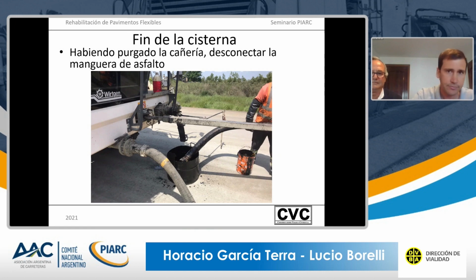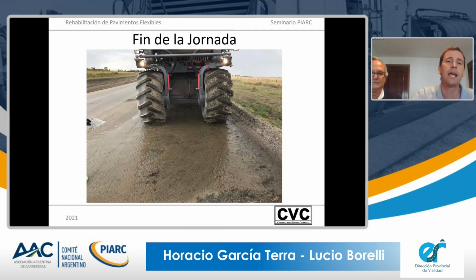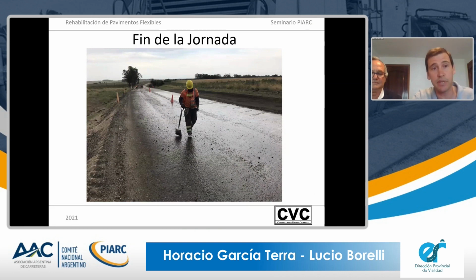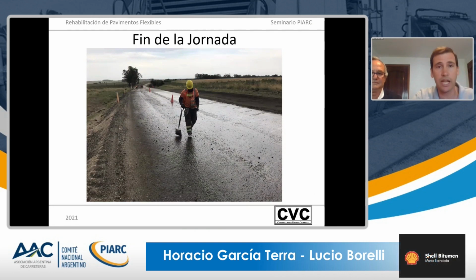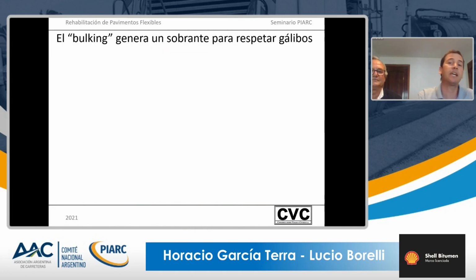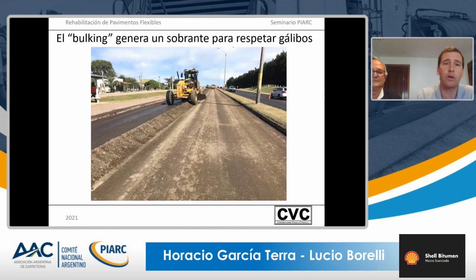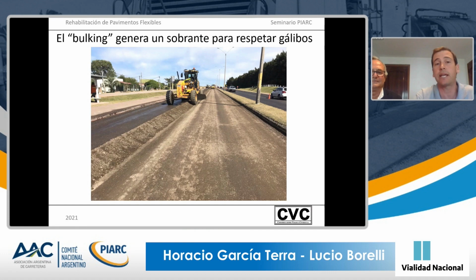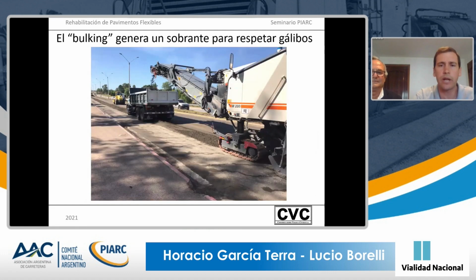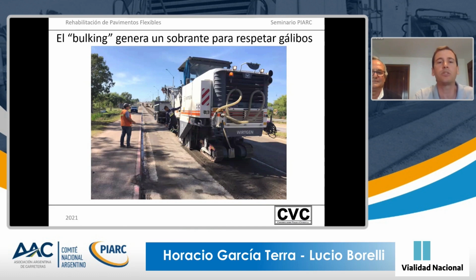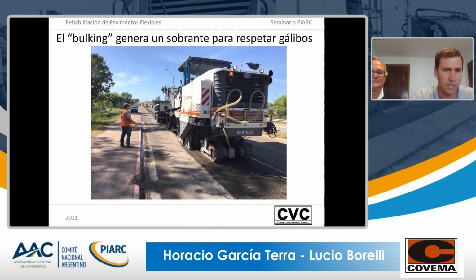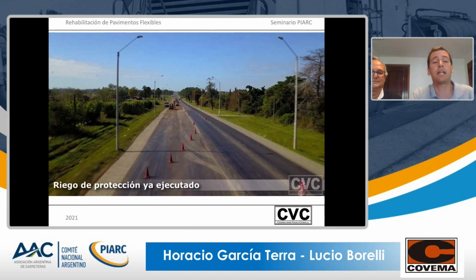Then, when we end the day, it's important to clean all the nozzles in the recycling machine, and this has to be done outside the recycling stretch, because if not, we will be creating some issues in the recycling stretch. In the case of Road 102, we need to remove the excess material, and this excess material was removed from the place, and the remaining material that was on the curb.